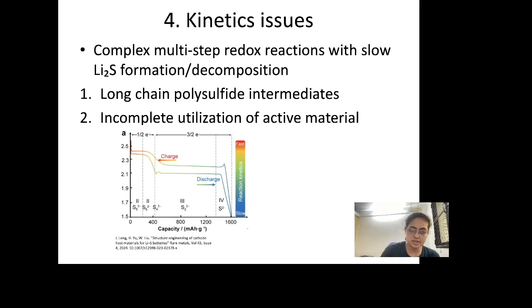But there are two points that we need to focus on in the kinetics issues. The first is that the intermediates in the reactions are long chain polysulfide intermediates, and this goes back to the old enemy of the lithium sulfur battery, which is the polysulfide shuttling effect, which means that when the reaction intermediates are these long chain polysulfides, these again get dissolved into the electrolyte, at least at the surface, and lead to a loss in sulfur, an exaggeration of the problem, and a huge loss of active material.